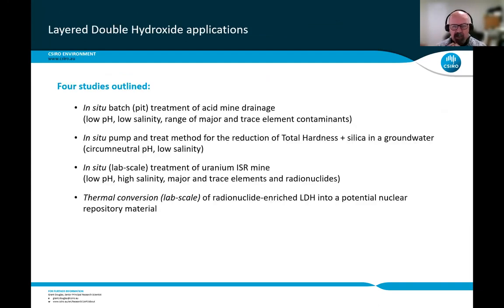So what I'll talk about now is 4 studies that we've undertaken with these layered double hydroxides. The first one being an in situ batch treatment of acid mine drainage, and that's low pH, low salinity, and a whole range of major and trace elements, including indium, which I think in 35 odd years of work, I'd only once ever come across before. And in fact, we were able to remove indium from this particular contaminated water. I'll also talk about an in situ pump and treat method for reduction of total hardness and silica in a groundwater, so circumneutral pH and low salinity.